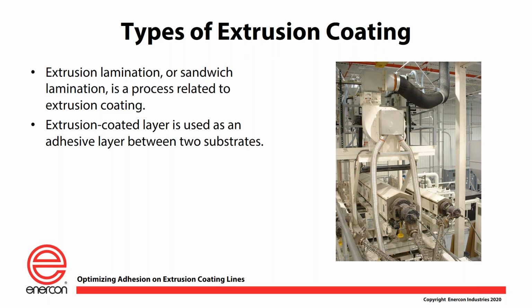The other type of extrusion coating involves lamination. That would be where the extrudate, like in my first example where you're using it just as a coating, is now used as an adhesive, and you can then use that to combine two other structures on the other side of it. So you could have a paper, the polyethylene, and maybe a foil as a structure, and the extrusion coating portion, that polyethylene in between those two products, is then used as a means of adhering the paper, let's say, and the foil in that case.